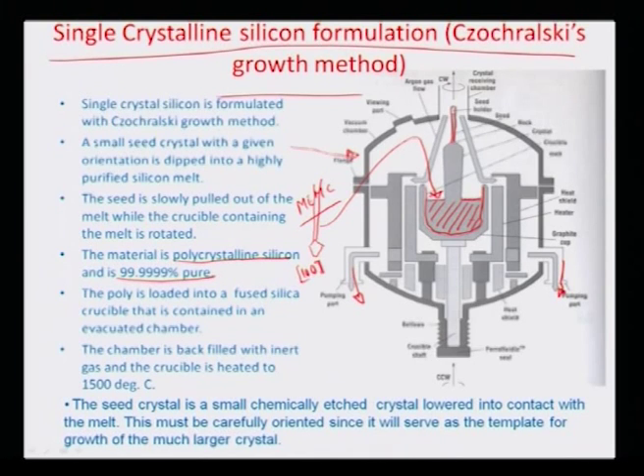And what is important here is that as the seed goes and dips into the material, and the seed is slowly pulled out, it tries to drag along with it a part of the silicon melt. And the moment the silicon melt comes out into the open atmosphere, it is no longer a part of the crucible, and therefore it can solidify. So the only advantage here is that the rates of solidification and pulling can be balanced with the rate at which the relative rotation happens between the crucible and the seed, and many other parameters are in a controlled manner.